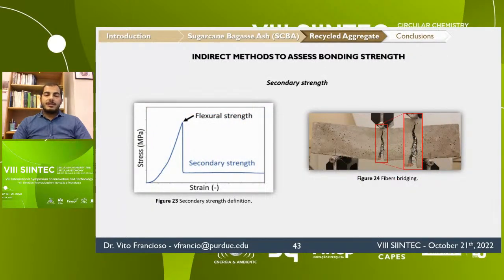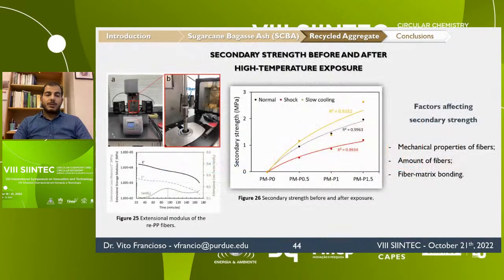Even though the recycled fibers did not remarkably affect the flexural strength, they have been found to increase the maximum strain before ultimate failure and provided the composite material a secondary flexural strength. So to evaluate the influence of exposure on the fibers bonding, I analyzed this secondary strength, since this strength is only related to the amount of fibers and the bonding between the fibers and the matrix. As we can see from figure 26, which presents the secondary strength of mortars before and after exposure, the higher the percentage of the fibers up to 1.5%, the higher the secondary strength.